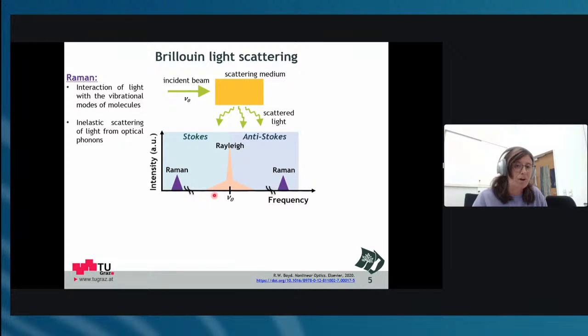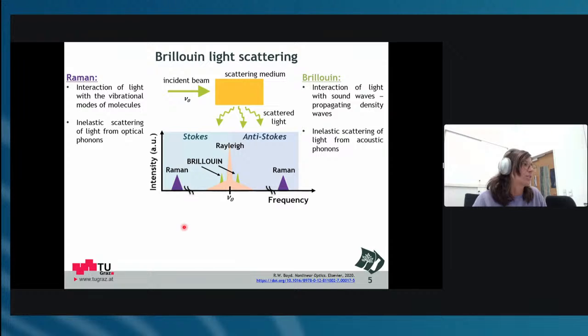So you get the shifts very far off of the zero line of the frequency. And usually these peaks are pretty intense. It's a very local interaction, and you can get chemical information of your material. And there is a second inelastic scattering mechanism, and that is Brillouin light scattering. So here you interact with acoustic phonons. It's an inelastic scattering of light from acoustic phonons, which have a lower energy. And that's why it's not very local, but rather a collective interaction. So the light is directly interacting with the sound waves in the material. Basically you're propagating density waves.